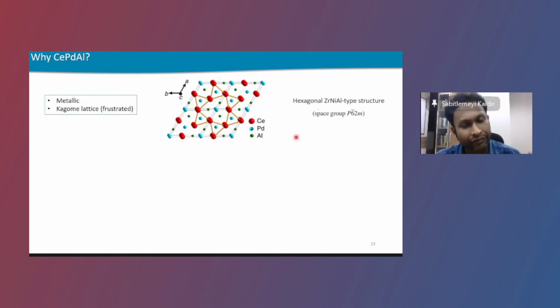It is a highly frustrated lattice, but of course the Kagome structure for this particular material is not a perfect Kagome, but some sort of distorted Kagome. But still it has some frustrated magnetic structure and frustrated arrangement of the cerium moments. Of course this system is metallic, and the other thing that we want is that the system must be